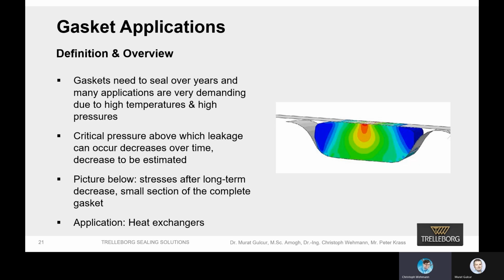And from the contact pressure decrease over time, and time again is a long time period, which means years, we can predict at which point it gets down to a critical level where we can have leakage. And that's how we carry out our lifetime predictions. We can do this at different temperatures too. And again, we use different elevated temperatures to have a material data input which can be transferred to a long time period.